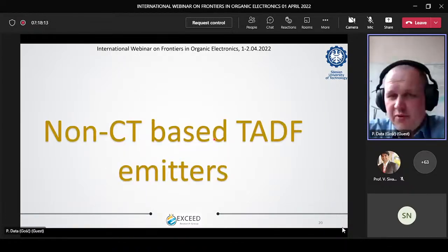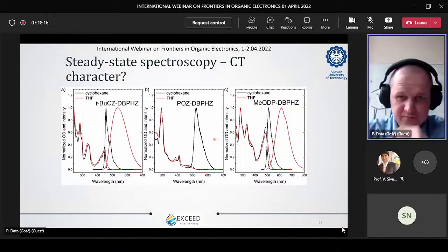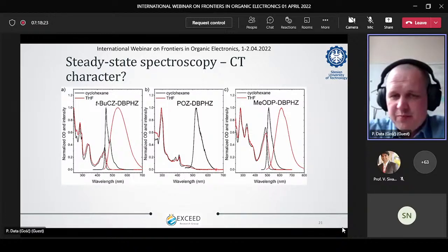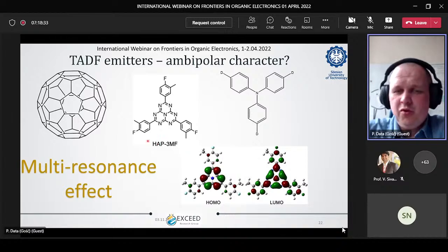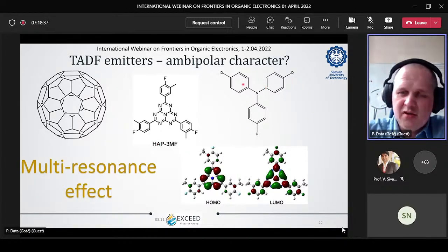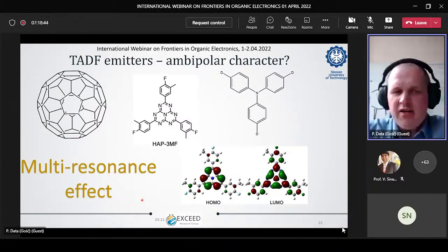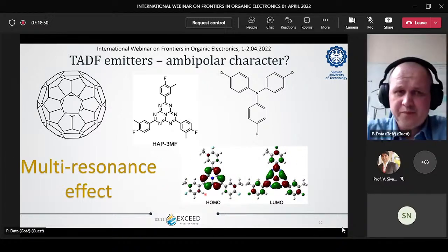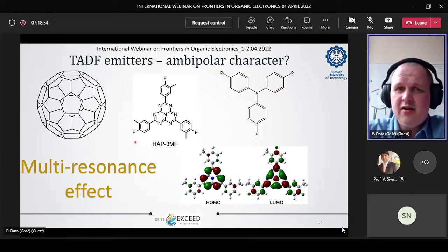How does the non-CT based TADF emitter look like? Like I told you, we have our localized emission, and in the spectroscopy, if in the polar solvent you will get exactly the same emission, which means we have non-CT emitter. Usually those are quite planar or symmetrical molecules, which have something called multi-resonance effect. Professor Hatakeyama presented different molecules which had such effect, and they don't have ambipolar character. There are usual acceptors or donors, and they also have TADF process.